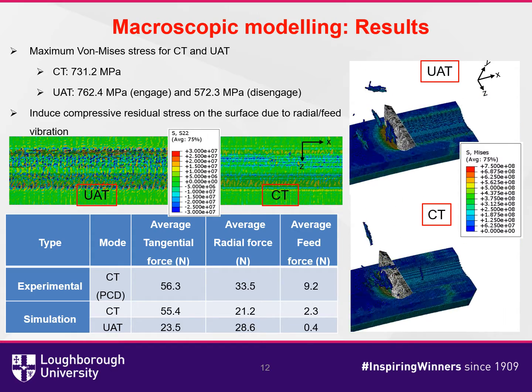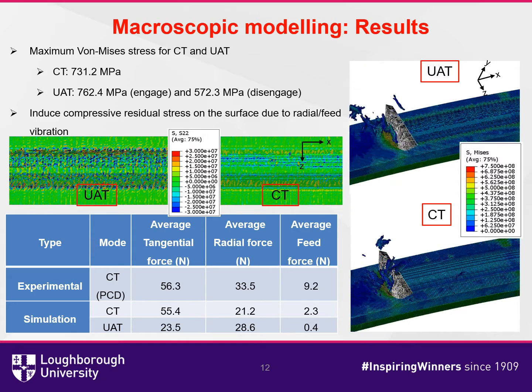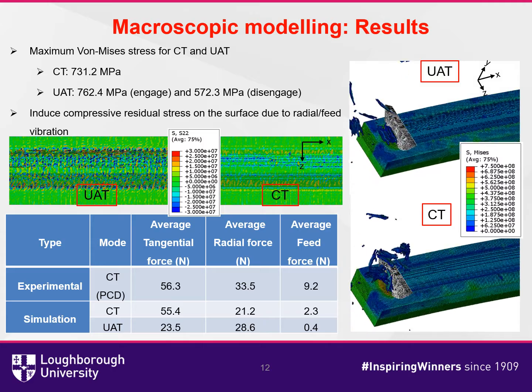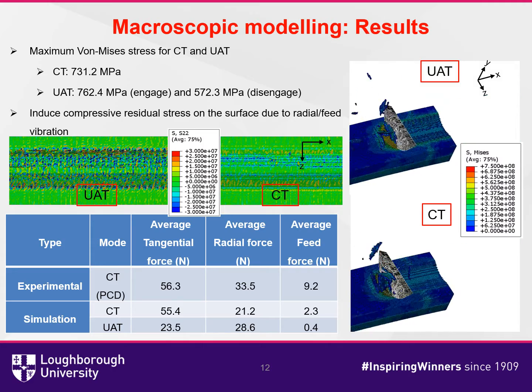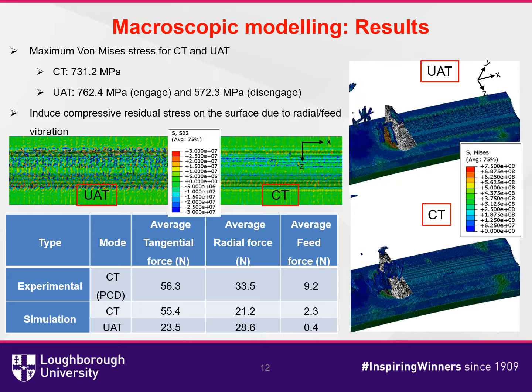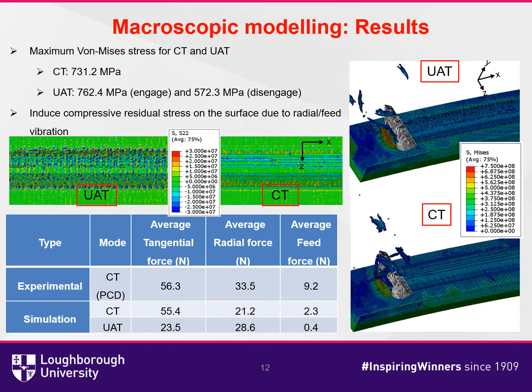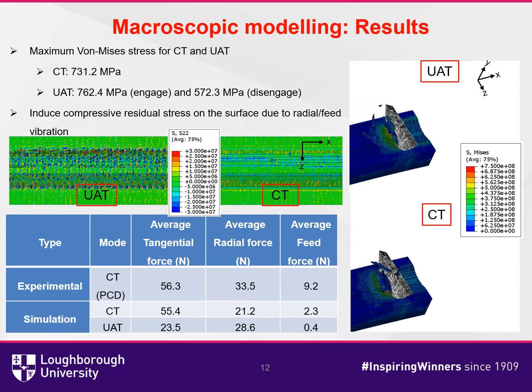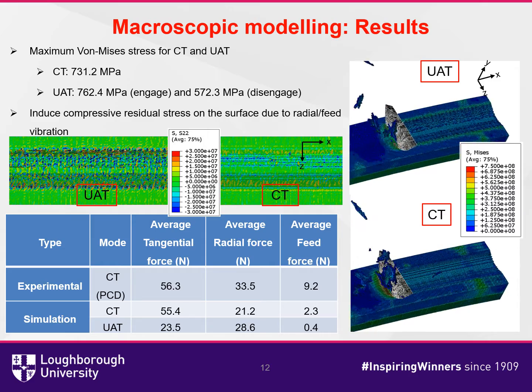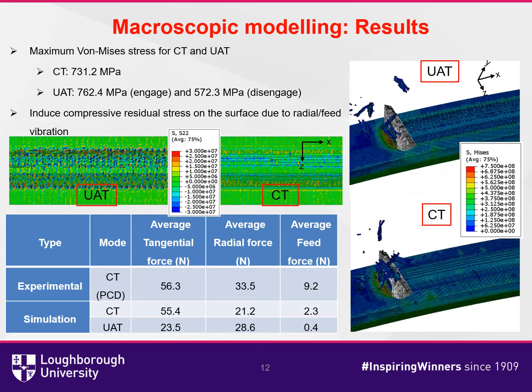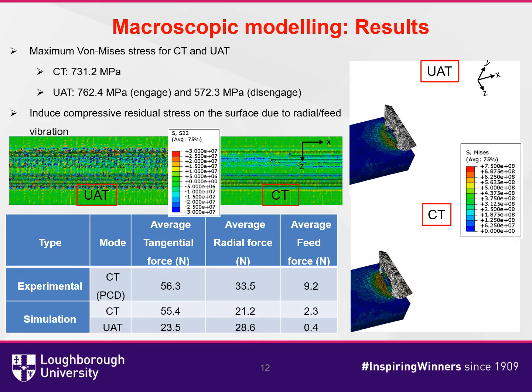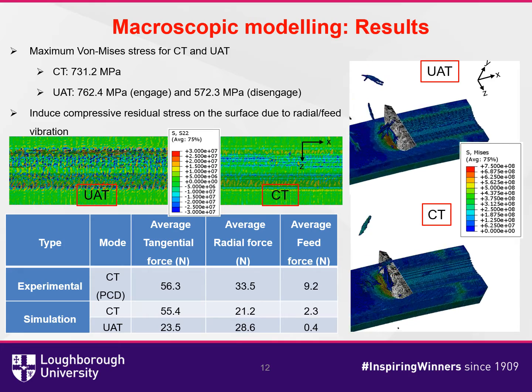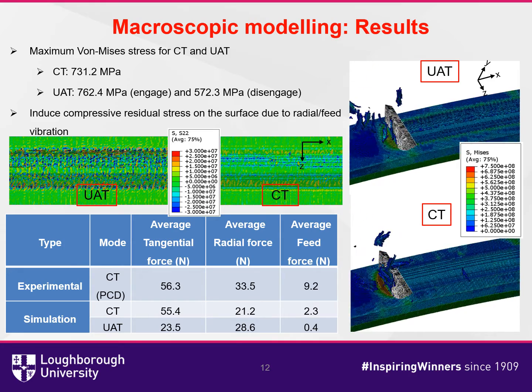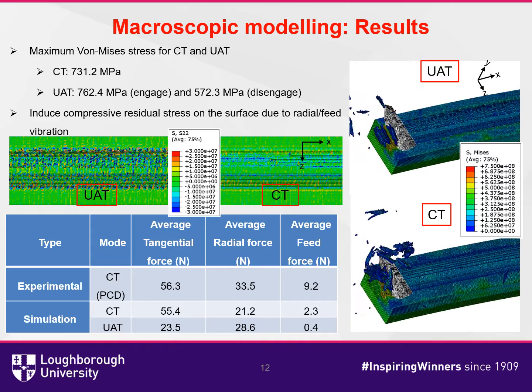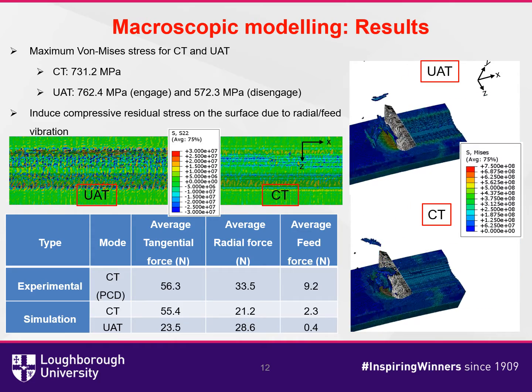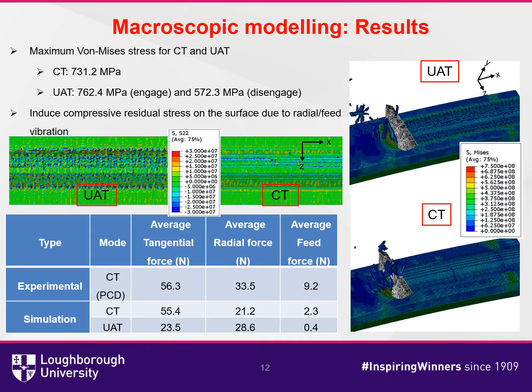The maximum stress in the shear band for UAT was higher than CT when engaged, but lower when disengaged, meaning UAT is adding more force onto the chip, but this continuous tool-chip interaction leads to improvement in the average cutting force and reduction of the tool-chip friction. Moreover, the 3D vibration is applying compressive residual stress on a larger area than CT, which in turn enhances the fatigue strength and life.